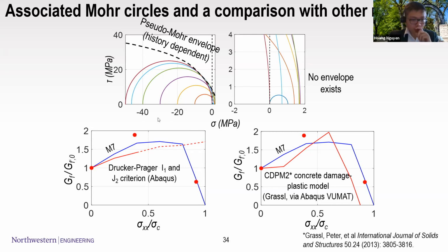And also another note on the type of the model that can simulate this phenomenon. So Drucker-Prager is one of the cases that we have failed to produce such a result, and you can see that it produced a wrong trend here. And we also examined the CDPM2, which is the tensorial model of the concrete, and you can see that because it captures some triaxial stress state behaviors, it can follow the trend of the data points, but not the values.